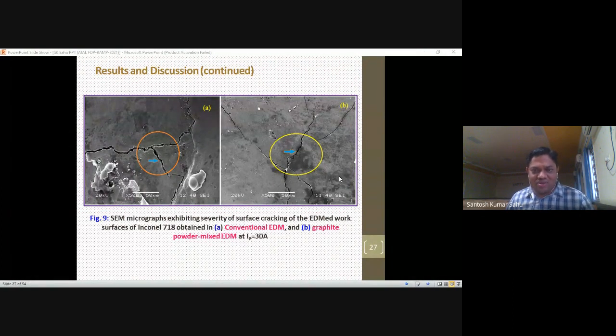Due to that, they may still be there, but the magnitude will be less, and this reduces the degree of severity of surface cracking. So that is another duty of the powder: not only to carry the spark, it also has to soak some localized temperature during machining. For that, we can minimize the magnitude of the developed stress, and also minimize the severity of the cracks.